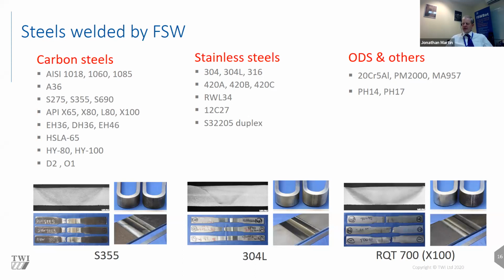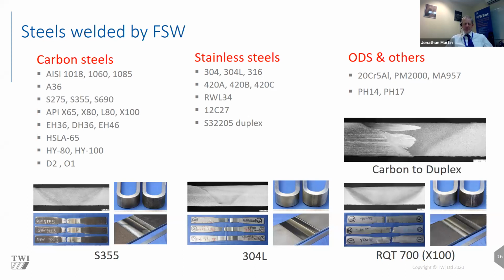And I think also with friction stir welding, it is possible to do some dissimilar joining. So this is an example of joining a carbon steel to a duplex steel. And I think universally throughout all this work and through papers that have been published, the properties of these welds are universally accepted as very, very good. This is due to the wrought microstructure of the nugget itself. So, reported increases in strength, fatigue properties, in toughness, etc. So I think this is universally known.